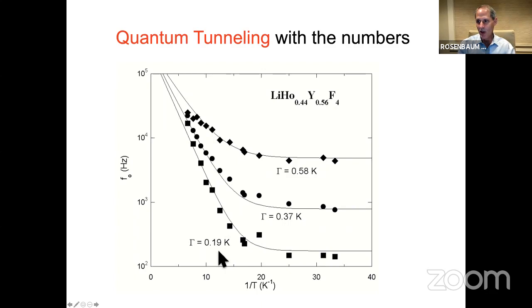So a lot of experiments on magnets, quantum magnets, depend on the fact that you go athermal at the lowest temperatures. There's no longer a thermal temperature dependence. And you say, well, that means I must be quantum. But of course, you could just be thermally decoupled. Here, we have the ability to manifestly put in the quantum mechanics and look at a series of different transverse fields indicated now by gamma. And you know that even though over this whole range it's flat, it's athermal, the gamma-T phase diagram continues to evolve throughout this region. So you know the system's responding. So this is a real indication of being dominated by a quantum process rather than a thermal process.